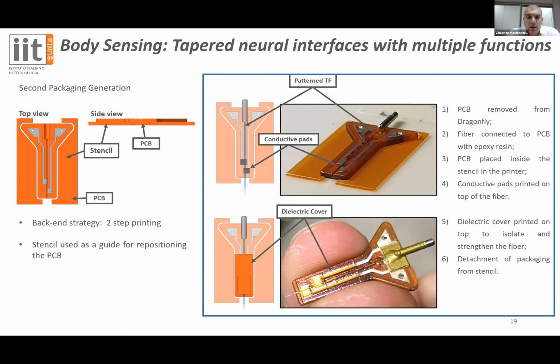Then the PCB is again placed inside the frame with a minimum alignment error, and after correcting the Z of the printhead, we printed again the second part of the PCB, printing first the conductive pads that are now directly in contact with the microstructured electrodes along the fiber, and the dielectric cover that completely embeds the fiber inside the PCB, making the fiber and the PCB itself more robust compared to the previous package generation.